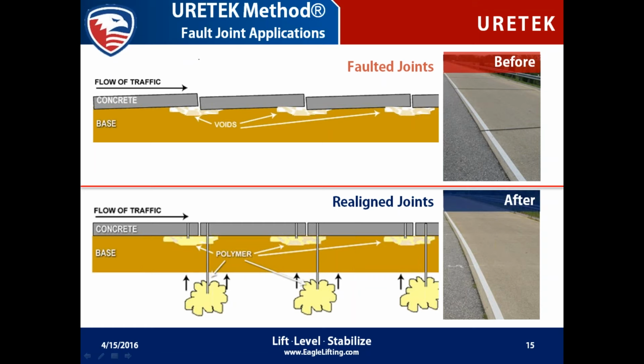In the after, before you look at the picture, you can see on the left-hand side in the diagram, polymers are injected at depth to strengthen the affected area of the soil, and then also injected directly through the concrete at the joints. This fills the voids that you can see in the top diagram with a structural polyurethane of 60+ psi, which you see in the bottom diagram. And by bridging that connection, you're restoring the strength of the slab and re-leveling. The re-leveling you can see in the after picture on the right-hand side.